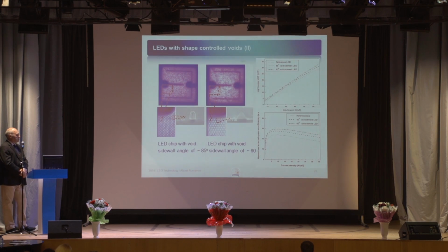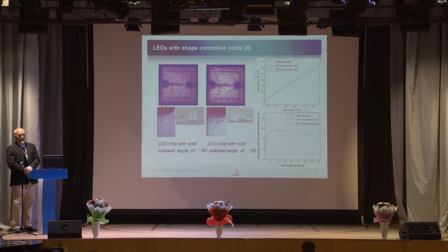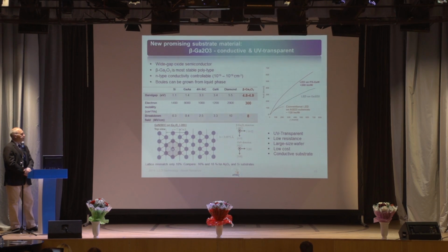And here I have the experimental data for the LED chips grown on such a patterned template. And it's possible to see, in this case, some increase in the efficacy. Not so big as we have expected, but still 15–20 additional % of light can be extracted from these structures. Still, the droop effect is not disappeared here.